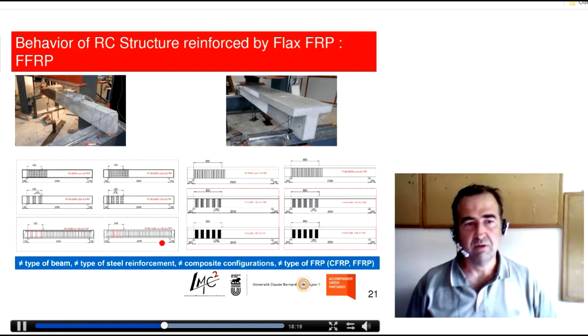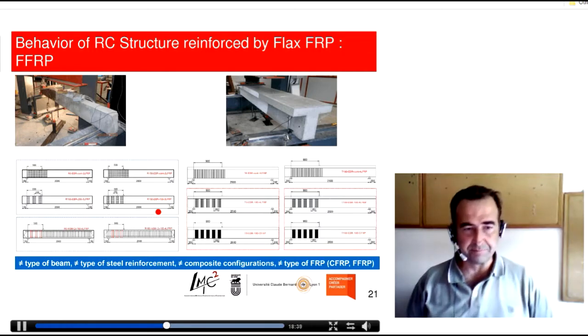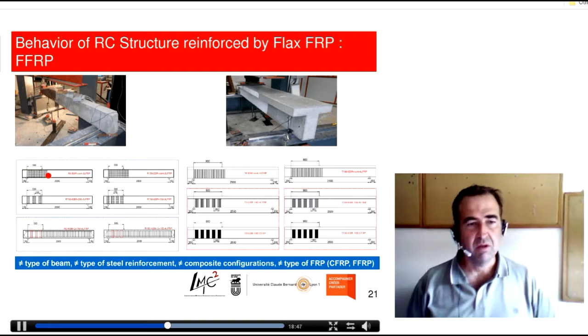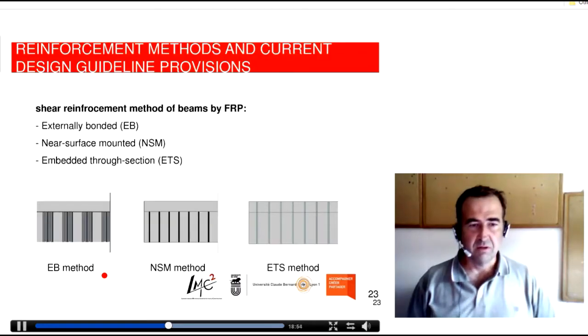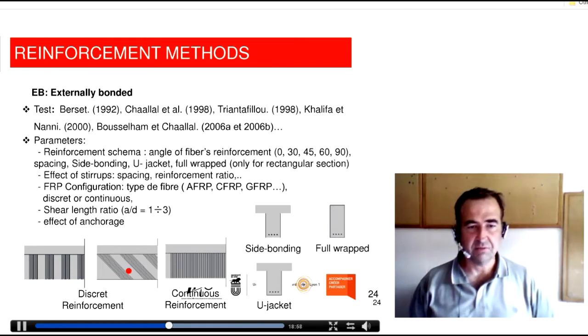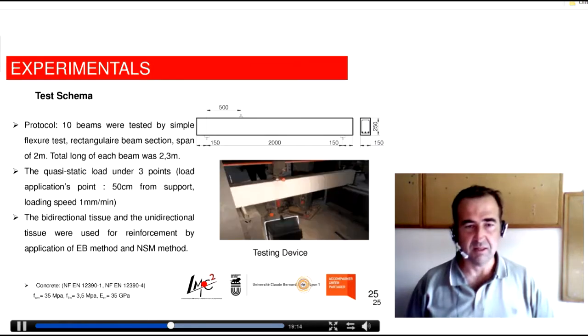So in a second PhD, what we've done is a first study about shear strengthening. We used two specific systems, a rectangular section and a T section, in order to evaluate the variability. On this, we have tested several different specimens, different spacing of the flax fibers, different widths, and also a continuous strengthening, and we'll compare this to the carbon method. You all know that there are different strengthening systems, and in our study, we mainly focus on this continuous strengthening.